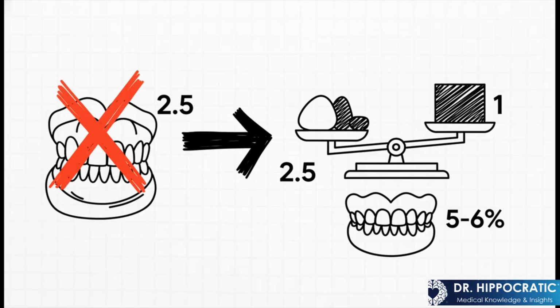And the solution is pretty brilliant, actually. We mix that liquid monomer with the pre-made polymer powder. See, that powder's already solid, it's stable, it's not going to shrink anymore. By mixing it in, we're basically pre-shrinking the vast majority of our material. Now, only the liquid monomer part has to polymerize and shrink. And by using that super precise 2.5-to-1 ratio by weight, we slash that massive shrinkage all the way down to a much more manageable 5 to 6%.